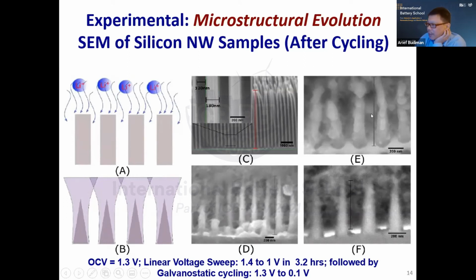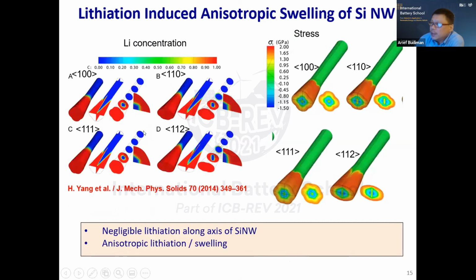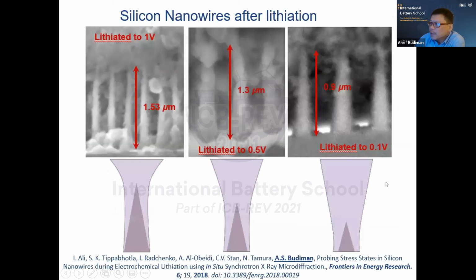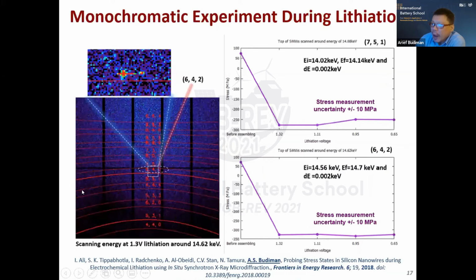You see that after some lithiation, you start seeing this cone structure, and the cone structure becoming smaller and smaller as this is going down and down until everything is lithiated. Okay, so this is actually just like what other people have proposed in their simulation. This is not our simulation, but this is basically what happens during lithiation of silicon nanowire, starting from the top all the way to the bottom, and how the stress is evolving. So you see again the lithiation happening and the cone getting smaller and smaller. From the X-ray, I'm going rather fast here because I think we are interested in what happens in terms of the implication for the performance of the battery, right? And also in terms of the path forward.